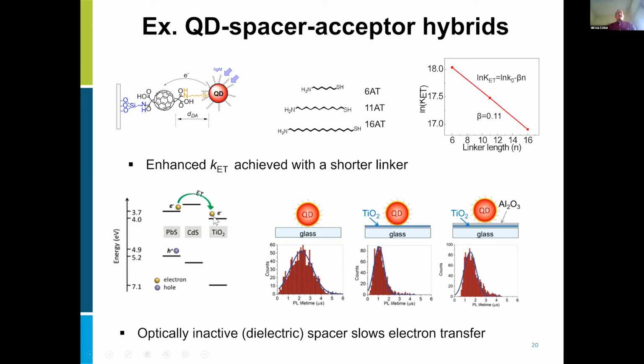Similarly, we can design systems based on near-infrared absorbing and emitting quantum dots like lead sulfide, where we have electron transfer with a titanium dioxide thin film. Quantum dots on glass, which is non-interacting, show long lifetimes on the microsecond time scale. When we put them on titanium dioxide, we see quenching, so the lifetime becomes extremely short. Adding a dielectric layer of aluminum oxide slows this down. This tells us that through the addition of this non-interacting layer, we can control the injection of the electron from the quantum dot core to the titanium dioxide.